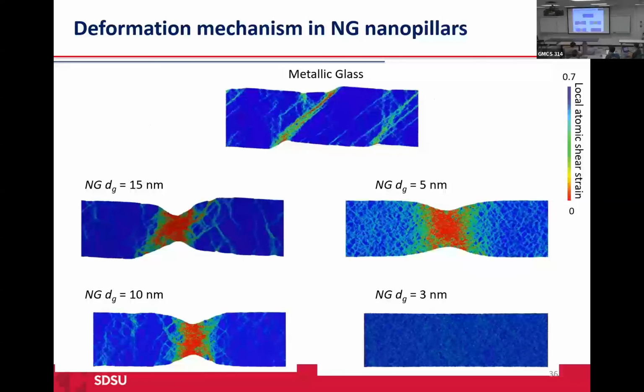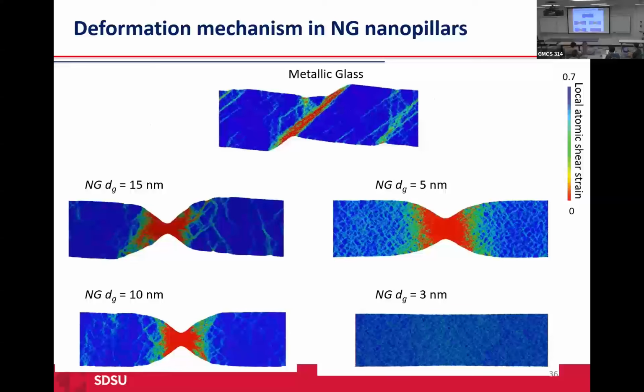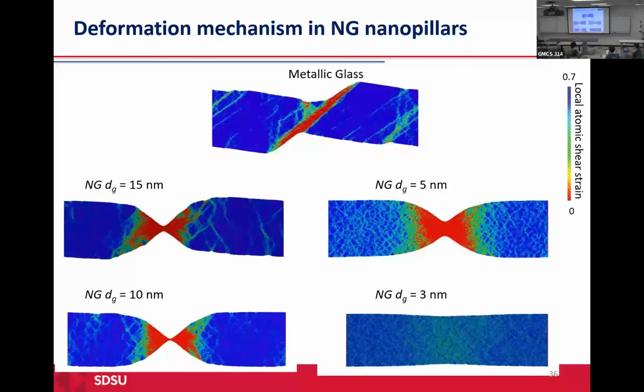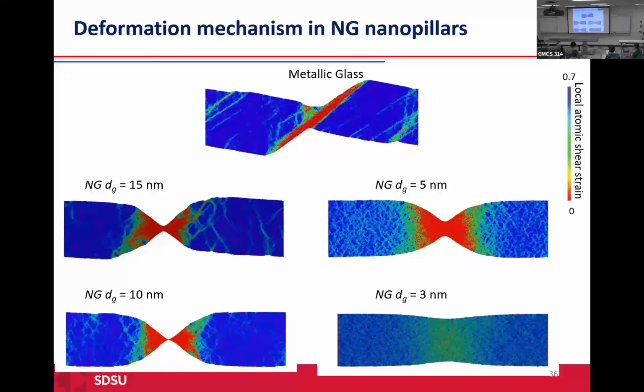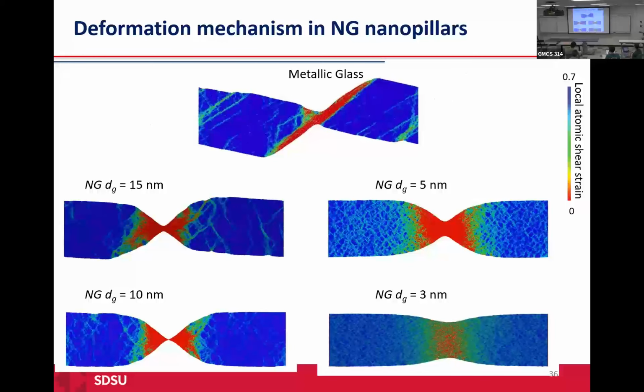Here is the result that we see under uniaxial loading. The top one shows just the metallic glass, which fails due to the formation of very rapid shear banding. As we go from the metallic glass to nanoglass, we have some plasticity because we can spread the formation of the shear band, and we have a network of shear bands. And then finally, we can see some necking behavior and plastic flow as well.